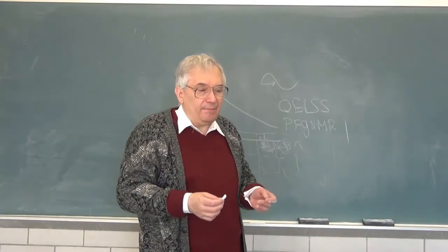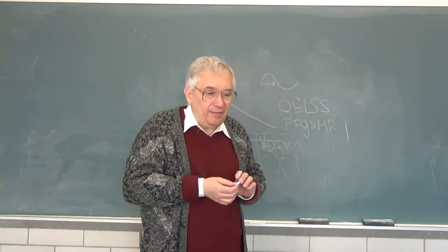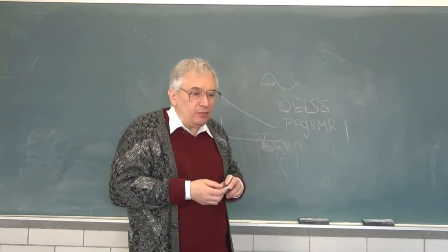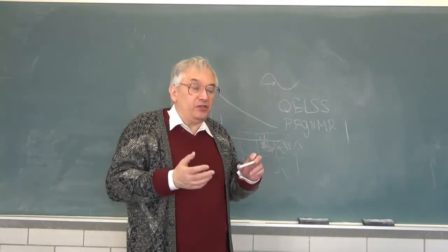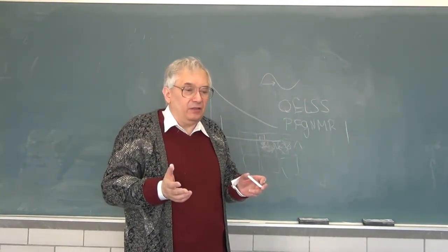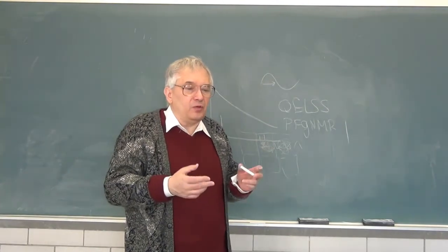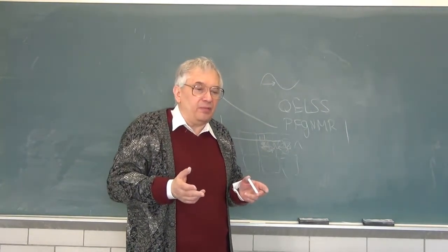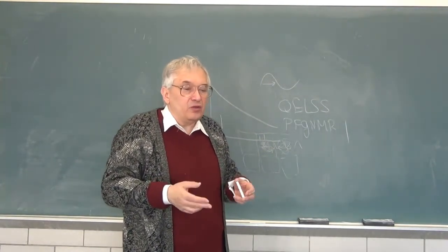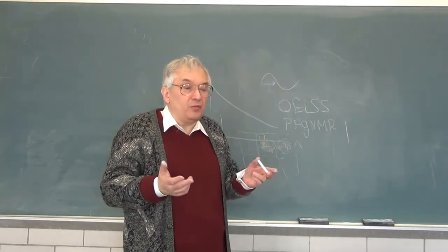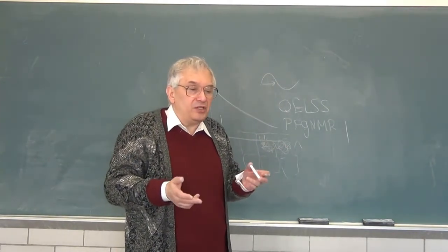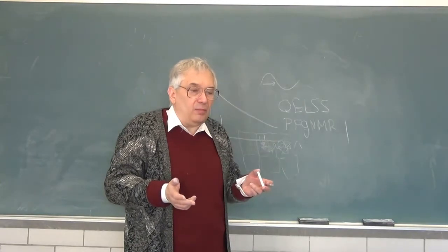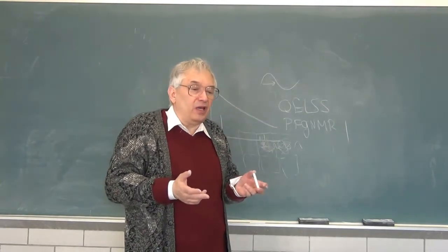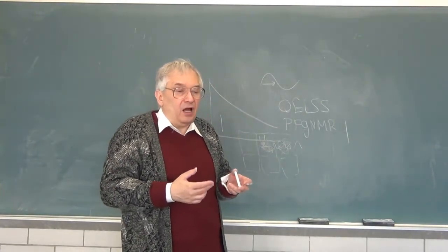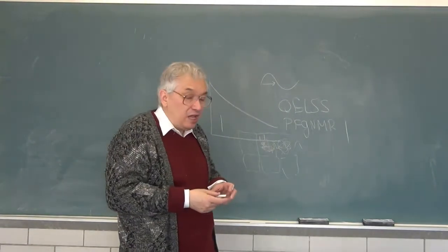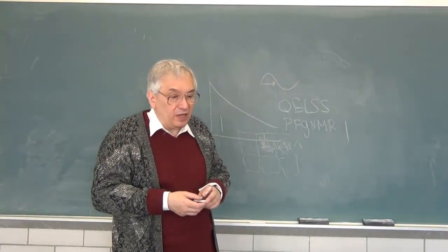Okay, we can now chug ahead. And you note, gee, this is 8 megadalton of polymer and up to 1.43 megadalton of polymer. So the probe and matrix polymers could be very large. And once again, though only the matrix molecular weight was varied, the matrix dependence is captured by the joint stretched exponential.